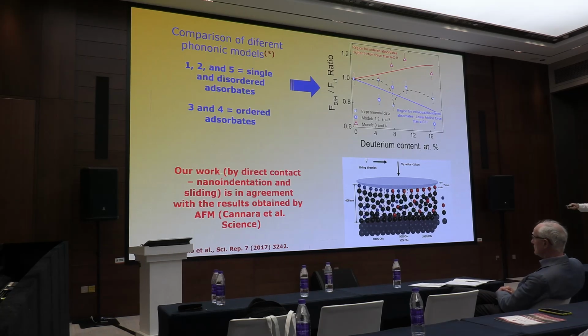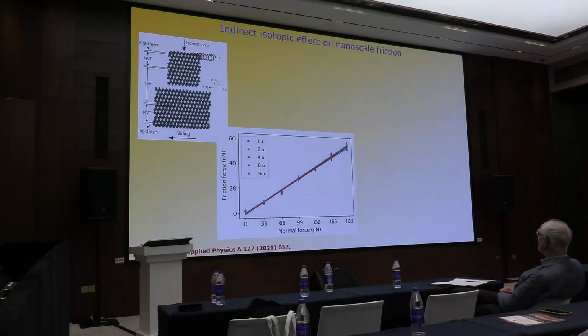In this case, our work by direct contact, by nanoindentation and sliding, is in agreement with the result obtained by AFM by Cannara, published in Science. We agree with Cannara, and disagree with the simulation from Isabella, from the other article. But after some time, a colleague in Brazil said, okay, for me, yes, I agree with Isabella. My simulation said that you don't have an effect of isotope. We started another work with other students, and we could see that the effect is not direct, it's indirect.